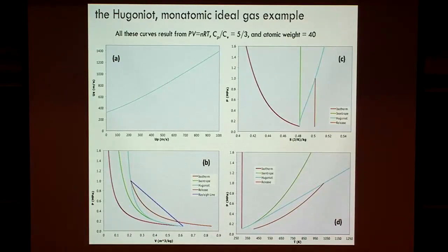I just wanted to ask, following up on Josh's question, to make sure I understand, that Rayleigh line of all the intermediate non-stable states, on that plot you showed earlier with the discontinuity, all of those Rayleigh states are on that discontinuity? Yeah, they're all compressed into that roughly 1 nanosecond. And then afterwards you're on the Hugoniot for a little bit before it decompresses and goes back down. Right. And the only reason to make a big deal about the Rayleigh line is just to emphasize what the Hugoniot is. The Hugoniot, unlike the isotherm or the isentrope, is not the path that you follow in a given experiment. It's the family of final states that you can get to by this type of experiment.